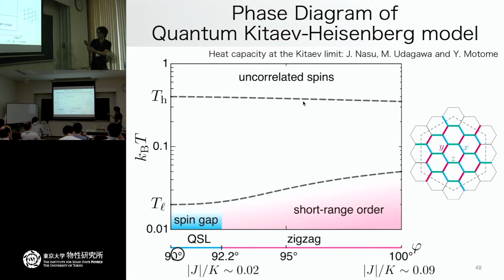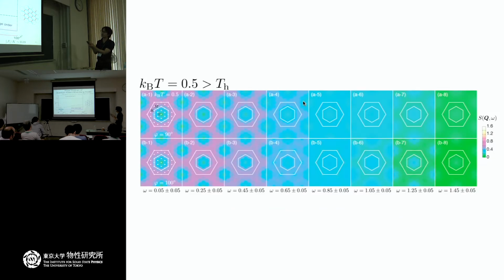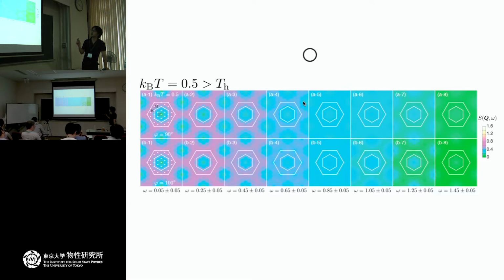Starting from this phase diagram, with the 24-site cluster of the Kitaev-Heisenberg model, if we change phi from 90 degrees to 100 degrees, we can cover the Kitaev spin liquid phase and the zigzag ordered phases. This temperature scale comes from the two-peak structure in the heat capacity. This is the high temperature peak temperature, and this is the low temperature peak temperature.